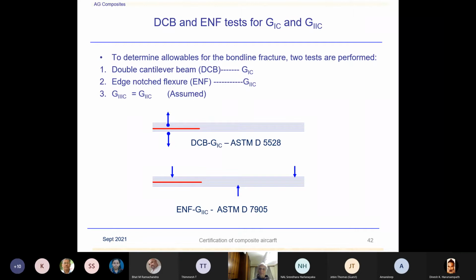Using a double cantilever beam specimen, determine G1C, mode 1 fracture toughness, and edge notched flexure, G2C. And usually the mode 3 value we would normally consider equal to mode 2, because the mode 3 test is difficult to perform in order to determine G3C. It is the usual practice, because that is also a shear mode, G3C equal to G2C is assumed. And I've shown roughly the schematic coupon over here.